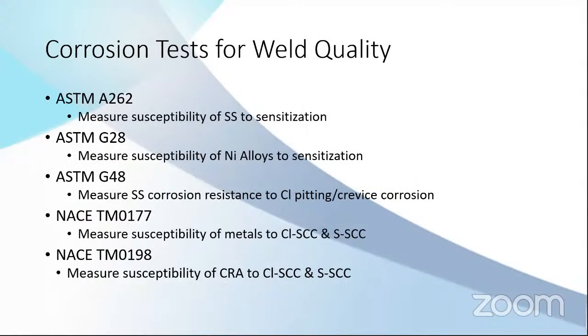And these are the most common corrosion tests to know the weld quality. ASTM A262, this is for the sensitization of stainless steel. G28, sensitization of nickel alloys. G48, resistance of stainless steel and nickel alloys to chloride pitting and crevice corrosion. Sorry, I forgot to add it. NACE TM0177 for chloride stress corrosion cracking and sulfide stress corrosion cracking of metals, carbon steel, stainless and nickel alloys. The TM0198 is for corrosion resistant alloys, stainless steel and nickel alloys, to chloride and sulfide stress corrosion cracking.